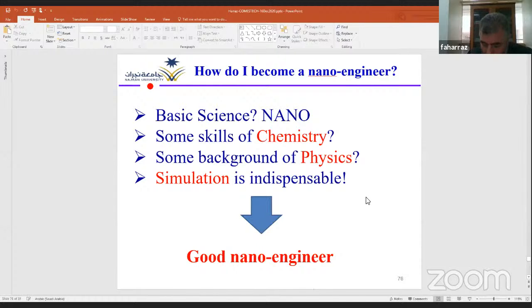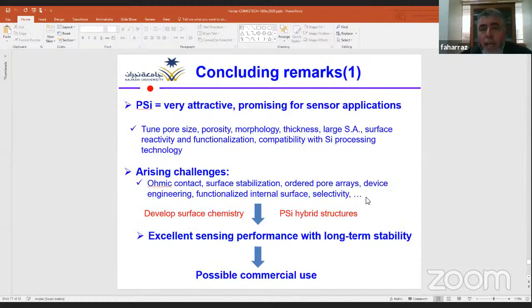Then we will be a good nano engineer. To conclude my talk, first part, porous silicon is actually a very attractive and interesting material in sensor application because the pore size can be tuned. Also, the porosity, morphology, and thickness can be organized with very large internal surface area. The surface reactivity and functionalization of porous silicon can be attained. And the interesting thing about porous silicon is that it is compatible with the existing silicon microtechnology.